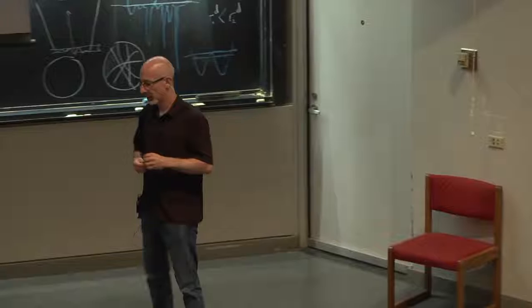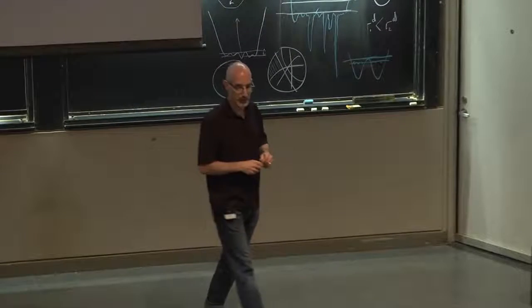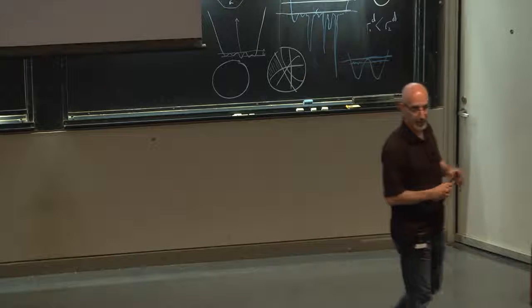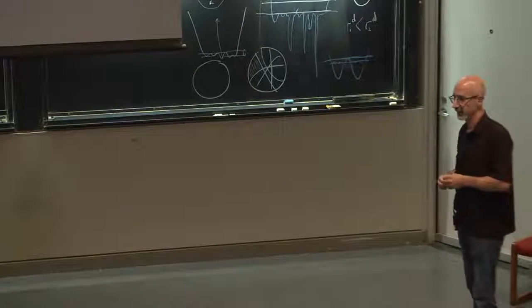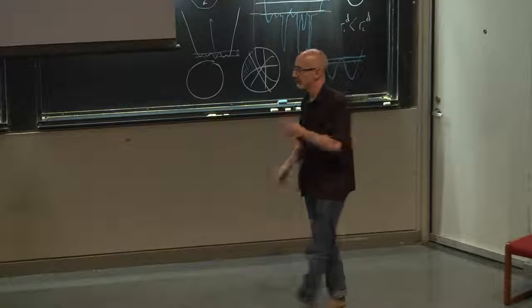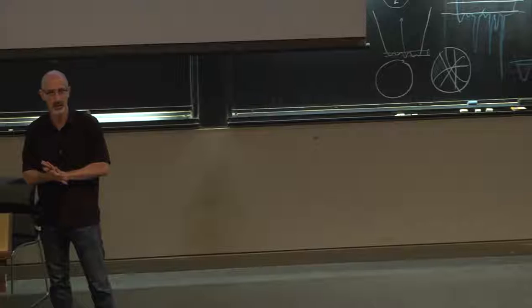So if I take SiO2 all the way down very close to the glass transition, the Stokes-Einstein relationship basically holds. So different systems will violate Stokes-Einstein to different degrees, and one of the things that I think is important to address is how this behavior is quantitatively connected to the other kinds of things that we'll talk about now.